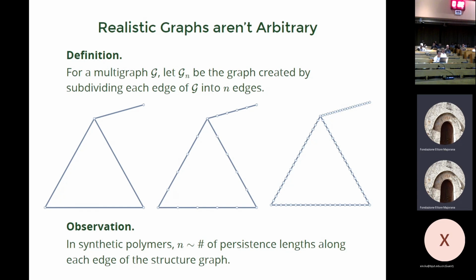So in these polymer models, typically your graphs are of this form, where I have a relatively simple underlying graph where I've now subdivided the edges many times. And so in this setting, all these little internal vertices are just degree 2 vertices. In the graph Laplacian, it's going to be very sparse, because you only get things showing up in the graph Laplacian when you have an actual edge between vertices. So on these vertices, their rows and columns are going to be almost all zeros in the graph Laplacian. So you have this very large but very sparse matrix. Surely you can do better than just dealing with the gigantic matrix.